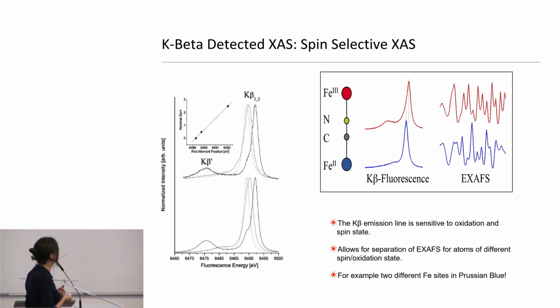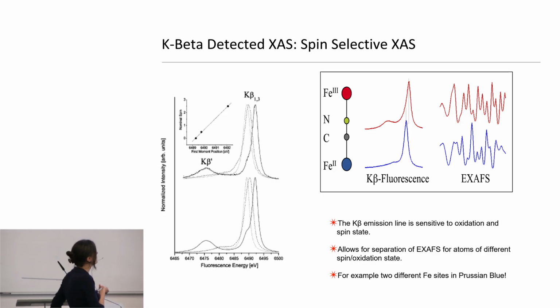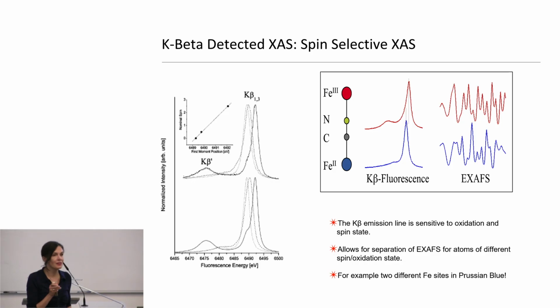Some cool experiments, but again, they remain in this sort of heroic regime, are things like using X-ray emission to get spin-selective XAS. And so the demonstration experiment on this was done by Pieter Glatzel on Prussian blue, where he actually was able to separate out the low spin iron 2 site and the high spin iron 3 site and get the XAS on those separately. Super cool experiment. Really hard to apply to many things in practice, but nevertheless, if you have very specific questions, there are places where you can think about this.